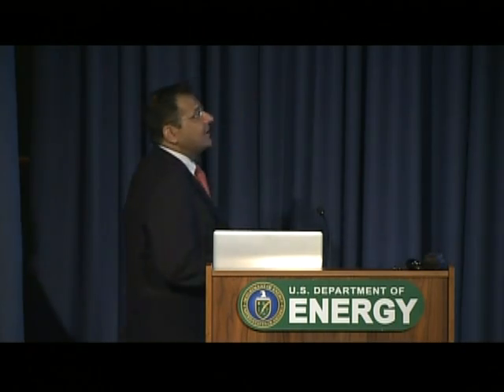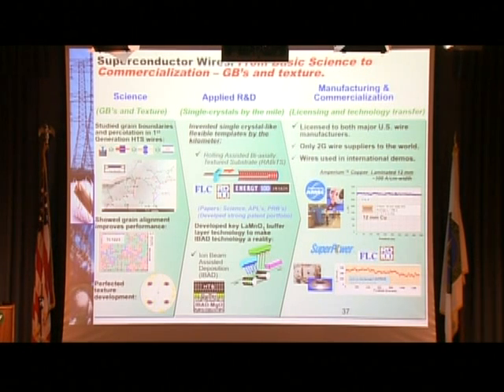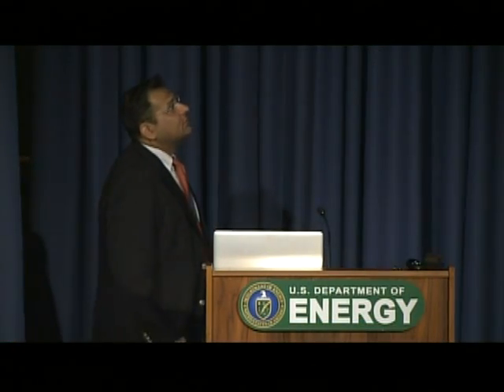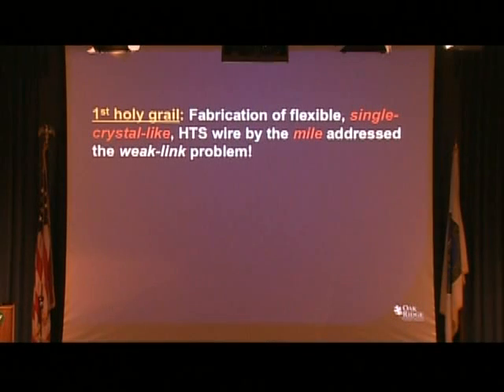So this is actually a very nice example, in my opinion, of taking basic science to commercialization. So we started with work which talked about grain boundaries in bismuth 2223. I didn't go into this thallium 1223 material, again related to texture, but we identified the need and we identified what we ideally need. We then used applied R&D to create single crystals by the mile, and then we transferred this technology to manufacturing and commercialization. Today, all wire made worldwide is made using one of these two techniques, high-temperature superconducting wire in all the countries.